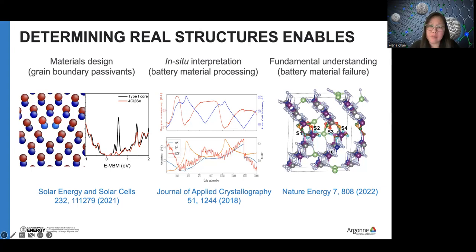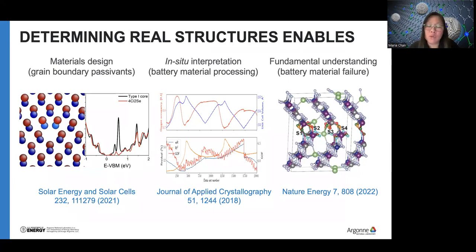In this particular case, this was an NMC battery material, and we were trying to understand the oxygen stability of this material. In batteries, one of the problems is when you charge it to very high voltage, oxygen sometimes becomes unstable. Our collaborator had a hypothesis that the interface is a particularly vulnerable point. So we carried out simulations of this oxygen removal energy, particularly at the interfaces that are experimentally observed, and found that indeed it was significantly easier to remove oxygen from there. This was published last year. So all of these examples show that having a real structure allows us to have deeper understanding, more realistic modeling, and so on. I think this direction has been fruitful so far.